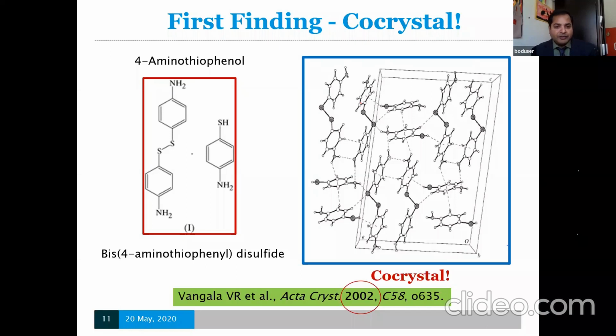I was looking into the intermolecular interactions in molecules that have functional groups of amine and phenol. Along those lines, we extended to look at the thiol SH group, similar to OH, and see if that has any complementary interactions between amine and thiol. What happened, interestingly, was we took aminothiophenol, which is a low melting solid, and we bought it from